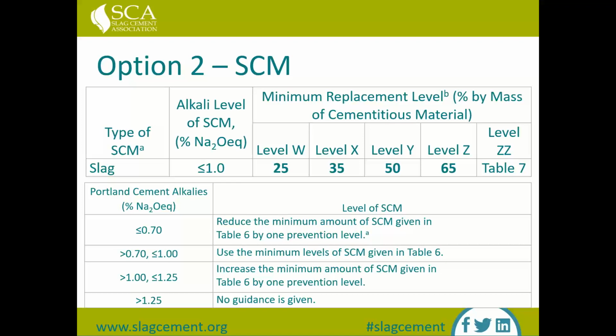On the other hand, if you're using a higher alkali cement, if the alkali content of your cement is 1.2%, now you move one column to the right, or increase one level. So if you need to mitigate to level X and you're using that higher alkali Portland cement, you now need to use 50% slag in order to achieve the proper mitigation.